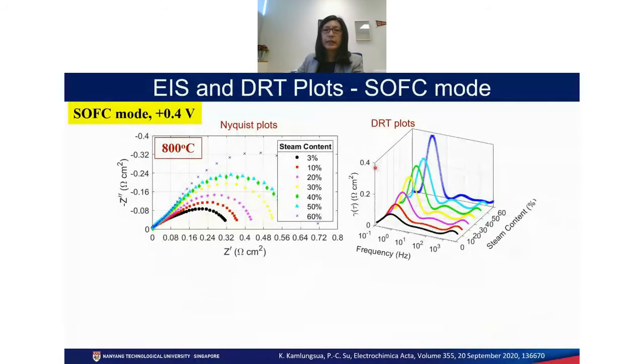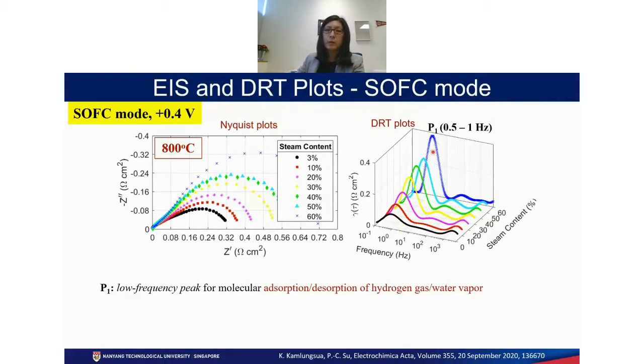So this is the first result, the EIS and DRT plot under the SOFC mode at 0.4 volt. You can see that the black one is the 3% water steam content, which is the lowest. As we continue to increase the moisture content, the impedance continues to increase. The DRT plot shows 3 distinctive characteristic peaks. The first peak is at low frequency, which accounts for the surface adsorption and desorption of hydrogen or water vapor. This is the main peak we look at, because we are changing the steam contents over the electrode, so this will be the most affected reaction by the changing moisture contents.